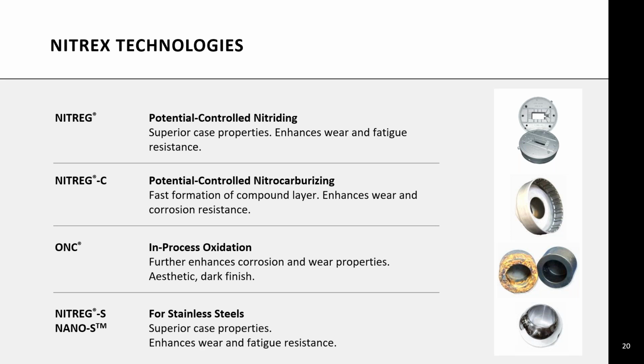Coming second after this was potential controlled nitrocarburizing. When we started first working on nitriding almost 40 years ago, 35 really, there wasn't much demand for nitrocarburizing. It was a process with very wide specifications. However, as companies started using lower and lower quality materials, more carbon steels, the demand for higher quality nitrocarburizing and better controlled processes arose. So we have developed this technology really very strongly for the last 20 years.